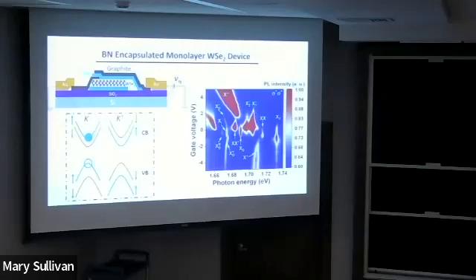For these two, you just add an electron in the system. The electron can be either here or here. These two configurations have different energy, different by exchange interaction, roughly 7 meV. So that's P trion, N trion 1, N trion 2. So these are all known before us. This is not a claim, but these are all well-known excitonic physics in the field at the time. But there are a lot of other features which were not known yet.